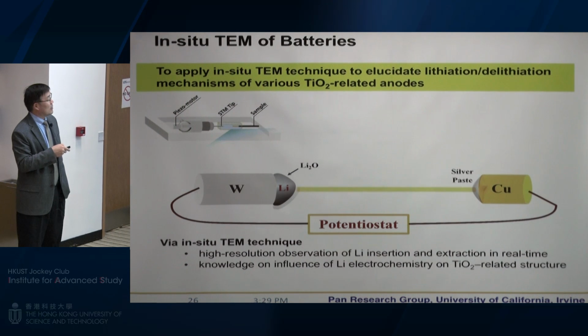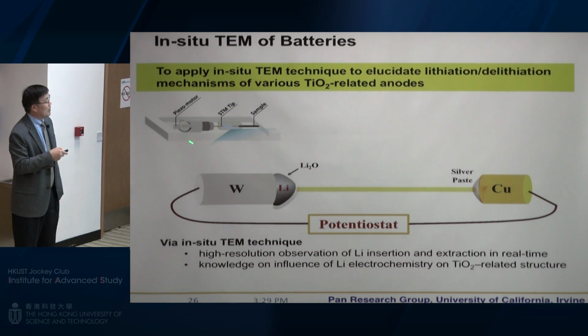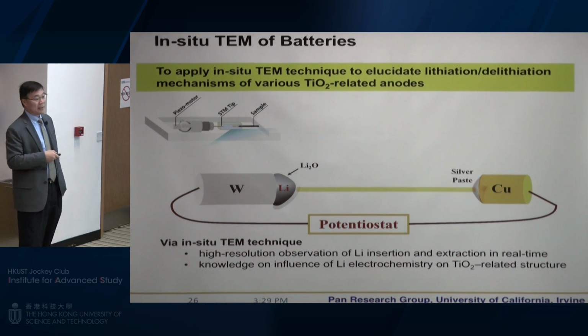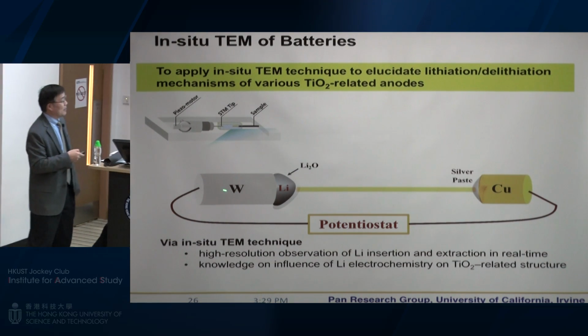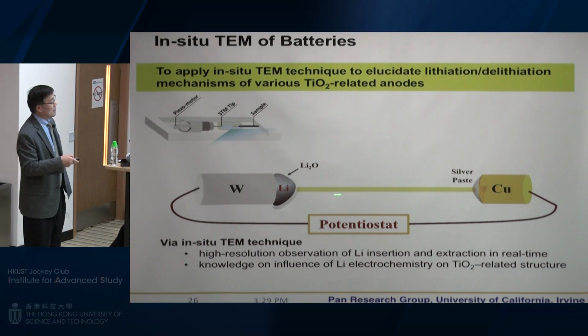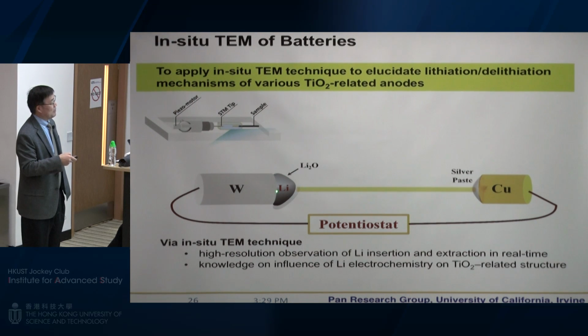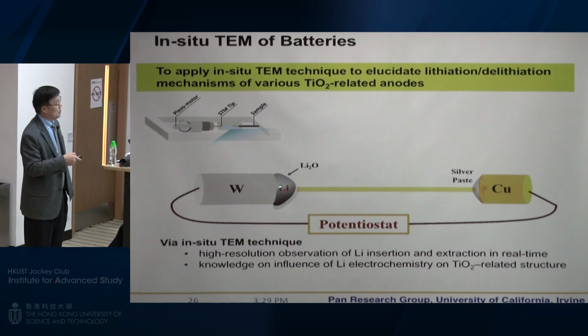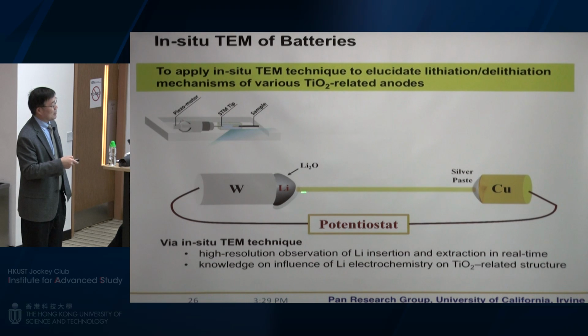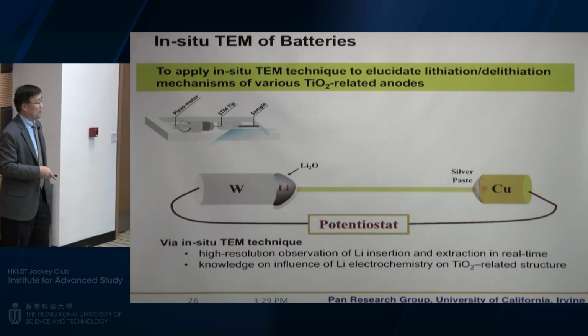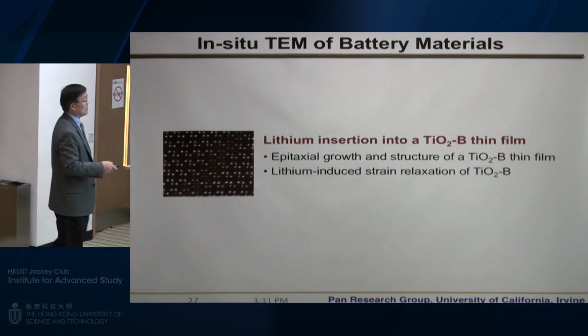So what we did is we modified our Nanofactory holder, and changed the biasing holder into a solid-state battery testing holder. If you use a nanowire, that is very easy to do. So you have one tip with lithium coated on it, and usually you have a thin layer of lithium oxide. Put the lithium oxide in contact with the wire. You have another post of copper, and then you can apply a field and see the structure and composition change.